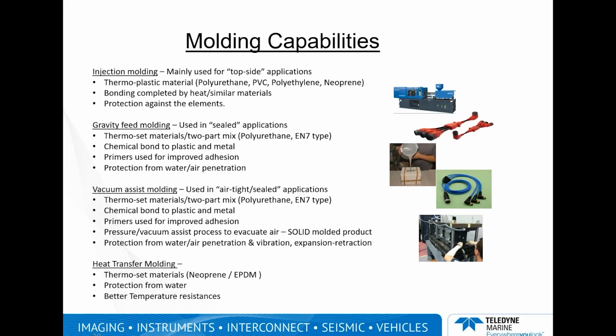Where this becomes particularly useful, we manufacture cable assemblies for missiles, for fighter jets, and one particular assembly that we manufacture is for ejection seats on fighter jets. What happens is if you get air bubbles into the mold form, and you've got a 30 gauge wire, which typically you do with these type of assemblies, the aircraft vibrates at a high frequency, 20 kilohertz. What'll happen is if there's any air bubbles, that 30 gauge wire, if it has an air bubble across that wire, it will vibrate. It basically creates a void, so it will vibrate and break.